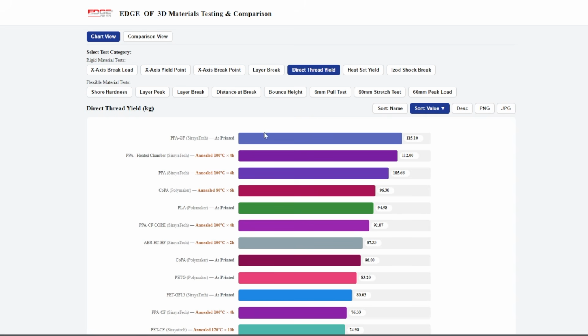So, layer adhesion. Here we go. PPA glass fiber by Siraya Tech, 115 kilograms of force to pull out the direct thread screw where it's threaded directly into the plastic. So that's where it's at the top.